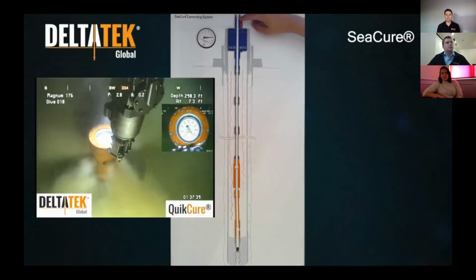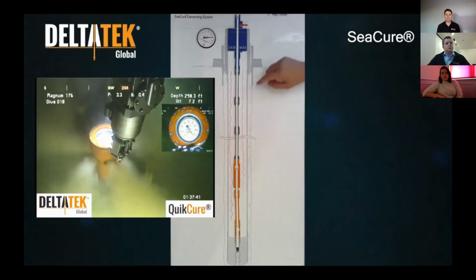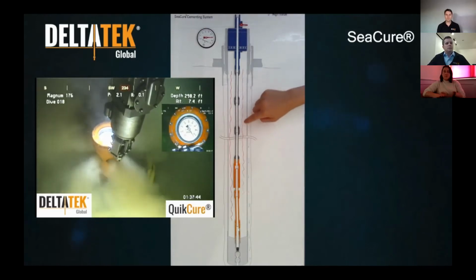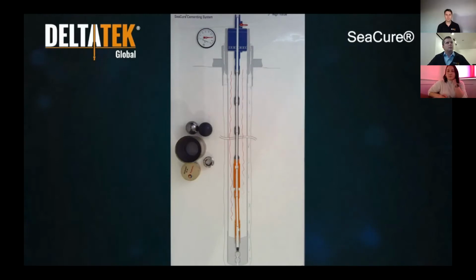At this point, the ball valve can be closed to allow the additional heat to soak through the casing wall and into the slurry. The additional heat causes a rapid build in compressive strength while reducing wait on cement time by up to 70% and improving transition time up to 50%.